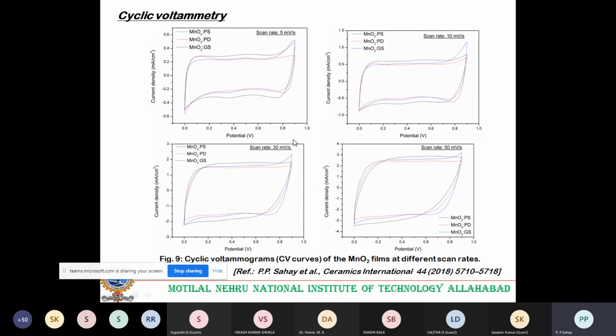So in the cyclic voltammetry, what we did here, this is the comparative study. Comparative study means all the 3 films at 5 millivolt scan rate, at 10 millivolt, 30 millivolt, and 50 millivolt scan rate. Okay. And from this one, we calculated the specific capacitance of the film.